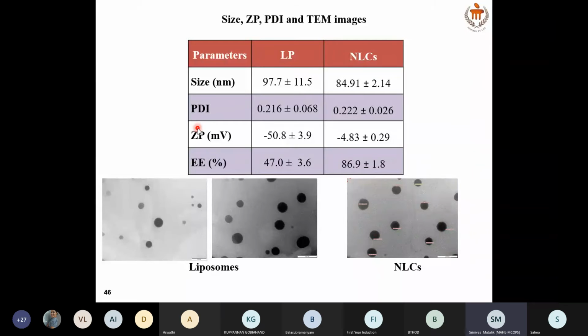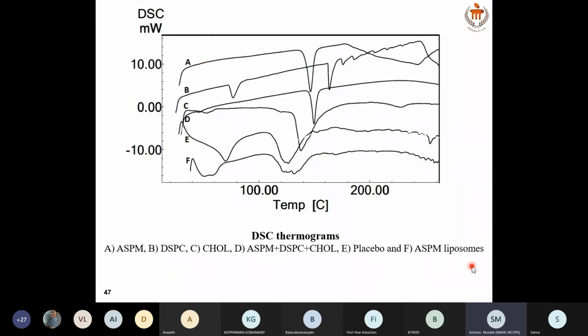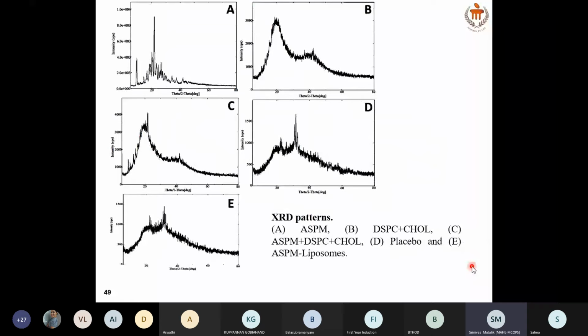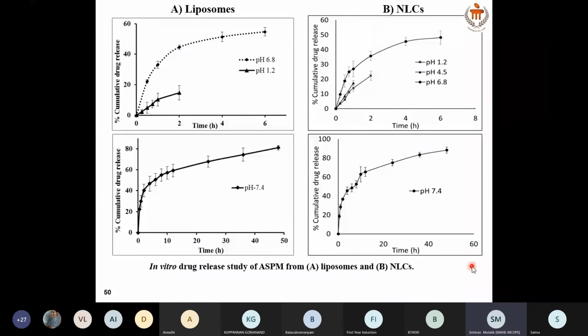These are the size, PDI, polydispersity index, zeta potential, and entrapment efficiency of liposome and NLCs. In NLCs, you can observe that the drug entrapment efficiency is almost double, and there were discrete lipidic nanoparticles for both liposomes as well as NLCs, which were in spherical shape as well. Many other parameters were tested, like thermal properties by differential scanning calorimetry, then the XRD for amorphization of the drug, and then drug release studies where the liposomes and NLCs showed prolonged release or sustained release of the drug for longer period of time.